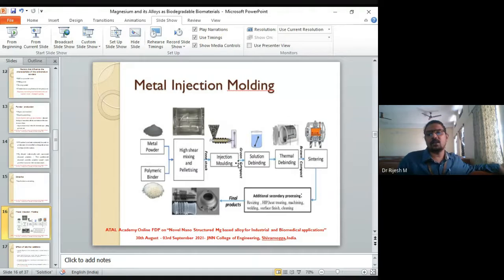Then we dip this product inside a solution, which is called solution debinding. Then we go to high temperatures, where you have thermal debinding. Still the material is not sintered. They are in the green state, so we take it to sintering, to a temperature which is less than the melting point of these powders. So when you sinter, you can see that the material gets densified.